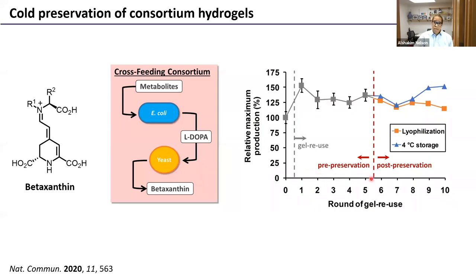An interesting experiment that we did here was that we're tracking the betaxanthin production. After the fifth round of reuse, we halted the experiment and we either lyophilized this gel or we stuck it in a refrigerator for cold storage. In the case of this lyophilized construct, we're removing all the water and we're left behind with just the polymer and the cells. And these constructs are shelf stable for up to 3 months.